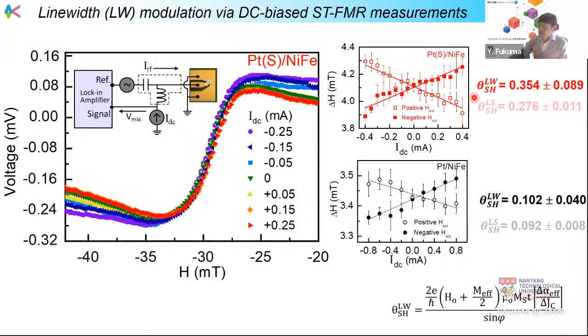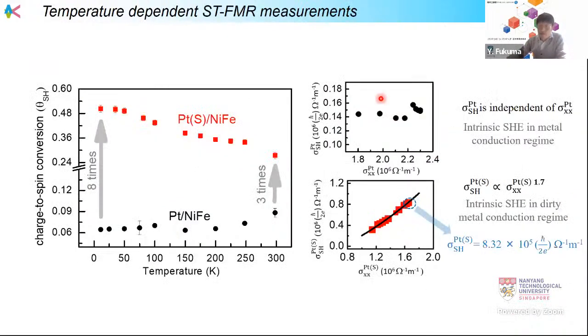What we can see here in the spectral analysis is that the spin Hall angle is a little bit different, but we can see a clear enhancement of the spin Hall effect for the sulfur implanted platinum layer. Also, here we measure the spin Hall effect as a function of temperature for the sulfur implanted platinum and the platinum.